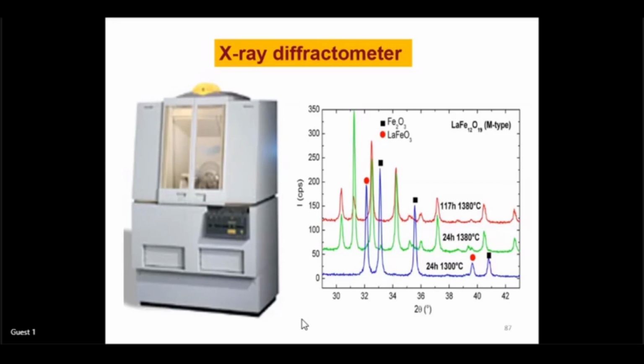And here, if you see, for the bottom one, the sample was heated for 24 hours at 1300 degrees centigrade, and again they have heated for 24 hours at 1380 degrees centigrade. Then what they have done, they have increased the time again to 117 hours at the same temperature. So here they are trying to increase the sintering hours, keeping the temperature constant. People also change the temperature. For example, at the bottom the temperature was 1300, then they increased it by just less than 100, to 1380. Time they have kept constant, but temperature is increased. And third, they have kept the temperature constant, but the number of hours increased.